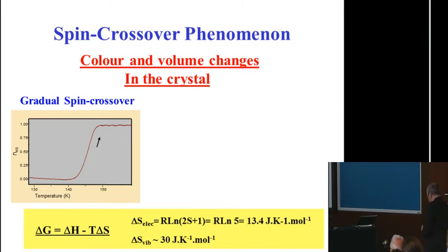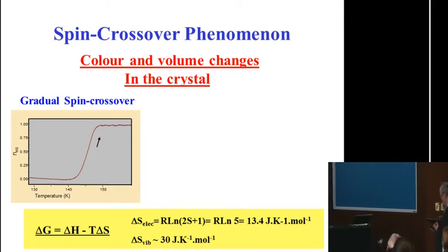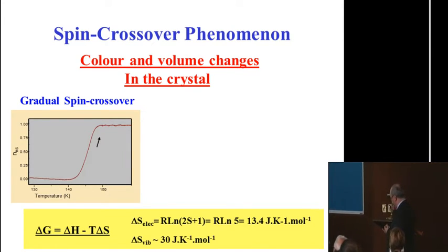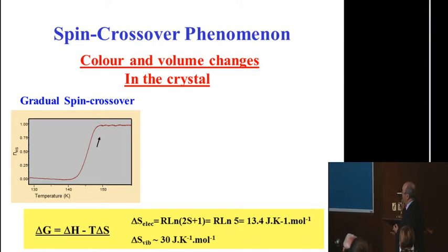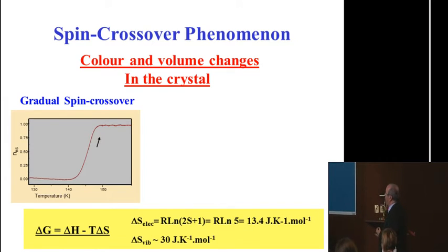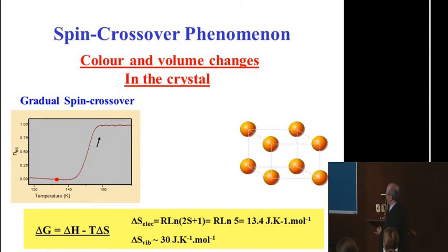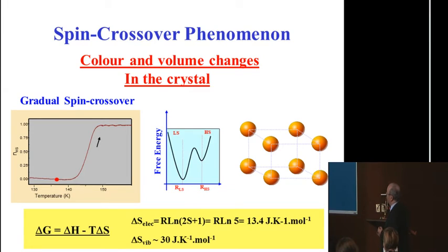So if we want to understand the mechanism of the spin crossover, if you take a spin crossover system, I take here a gradual spin crossover. When you prepare it at low temperature in the low spin state, if you look at the crystal, the system is mainly in the low spin. If you look at the energy of the system, we call that its double well potential, okay? This is the free energy as a function of the distance between molecules.